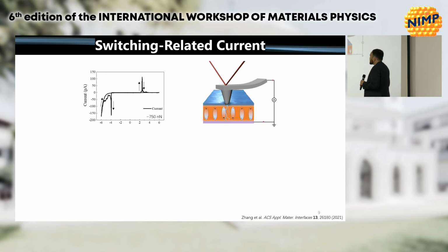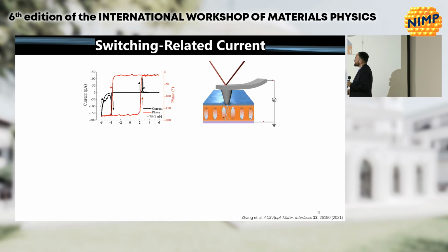Okay, so now if we look at this switching-related current, here's an IV curve showing switching, again, at the location where we were just seeing that we saw switching take place. We can map that at the same time with our PFM phase loop, and you can see that the switching takes place and the high current takes place when we have the polarization reversal. And this was recorded at 750 nanonewtons.